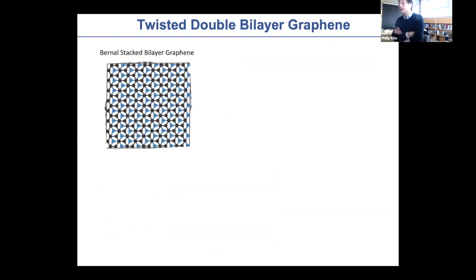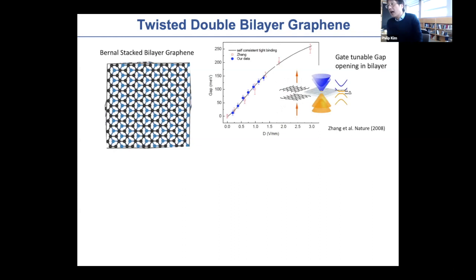If you just think about the Bernal stacked bilayer, just two graphene layers stacked into registry, basically there's inversion symmetry between the lattice points. So if you break this inversion symmetry of the Bernal stacked bilayer, in fact you can open up the gap at the charge neutrality point of the spectrum. And this has been demonstrated by many experimental groups, by optical measurement and transport measurement, by applying a displacement field in the vertical direction of this plane. One can open up a gap of the size of something like even 100 millielectron volts.